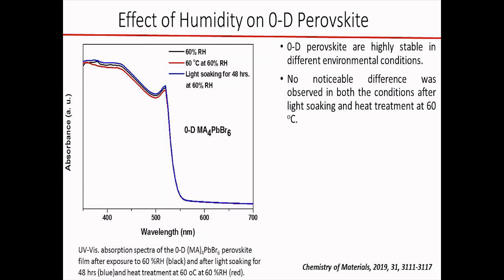This is also very stable at 60% RH, because the material is forming only at 60% RH, so that's the reason why this is very highly stable. We also studied it at 60 degrees centigrade temperature at 60% RH, and still there is no noticeable difference observed for this film.